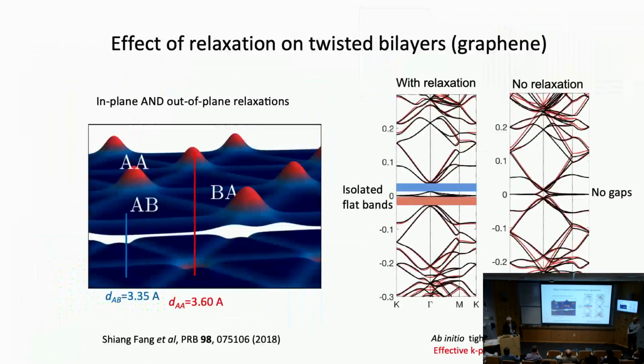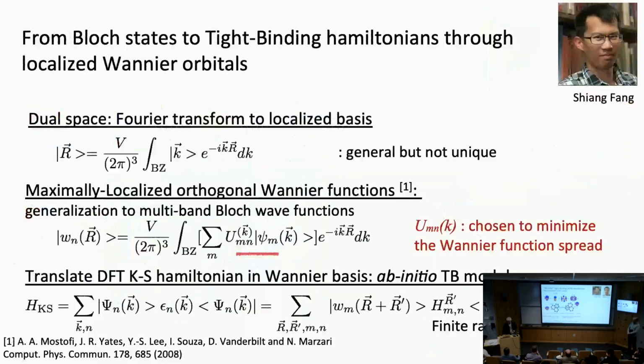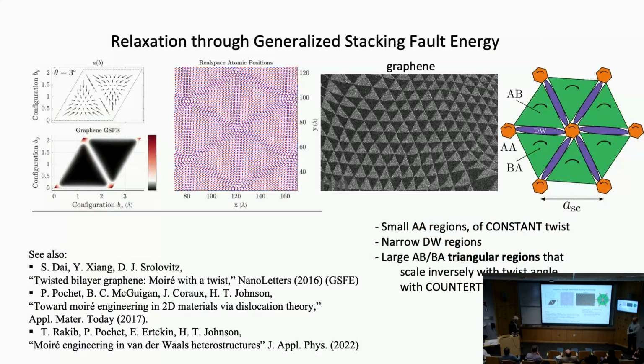And that's why I was also trying to bring in the importance of the relaxation, which clearly tells you that it's not a triangular lattice. If you look at this, the orange hexagons make a triangular lattice, but the green triangles make a honeycomb lattice, and the domain walls make a Kagome lattice. And you can't forget them, because the states have weight in all these three regions, and they're coupled. So you have a huge degeneracy, which is frustration.